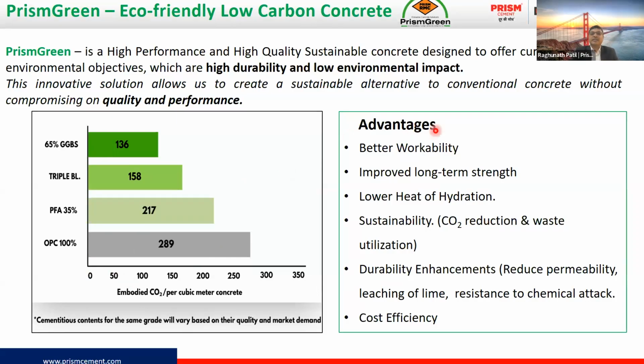So here are some of the advantages of this green concrete. Better workability, because we use pozzolanic material like fly ash. Fly ash has spherical particles, and these spherical particles work with a ball bearing effect, which reduces the water demand in the concrete. So it improves the workability. Long term strength gain, since the pozzolanic material continues strength gain for a longer period, and it makes the microstructure of concrete minimize the voids, and continues the strength gain beyond 28 days of age. Lower heat of hydration. In case of mass concrete, it is very useful because we replace the cement, and hence that much heat is directly reduced, and we can control the thermal cracking in mass concrete.